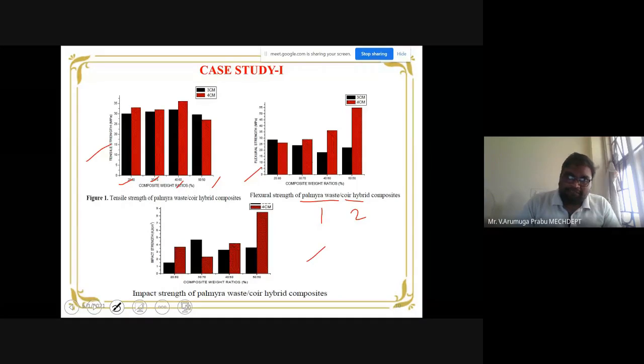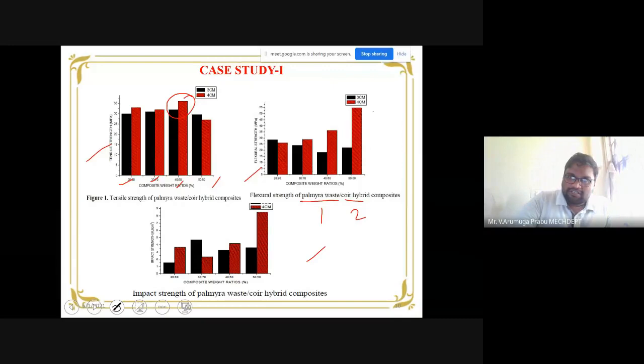So among these four types of composite combinations we made, in all the cases, we are able to notice the enhancement in strength. In the first case, tensile strength, the highest strength is noticed in the combination of 40 is to 60. In the case of flexural strength, it is noticed in the case of 50 is to 50. In the impact strength also, it is noticed in the 50 is to 50 combination.